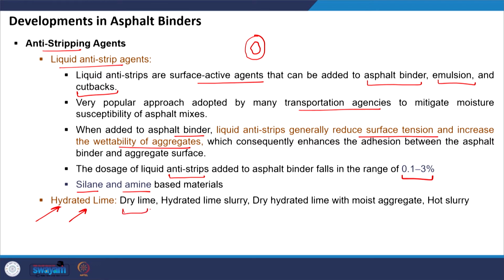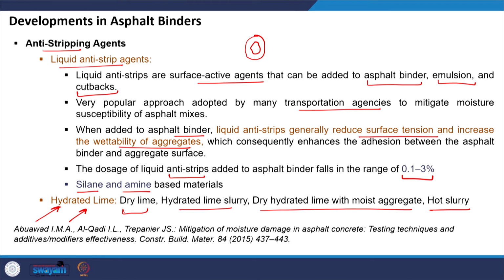We can add dry lime, we can add hydrated lime slurry, we can add dry hydrated lime with moist aggregate, again the reaction will lead to the formation of further products. Some researchers have also added it in the form of hot slurry, and the process of addition will also finally affect the extent of resistance to moisture damage the hydrated lime will provide. So, it is important that we decide which process should be adopted. So, this is one of the papers you can refer to for knowing more about the moisture damage in asphalt mixtures.